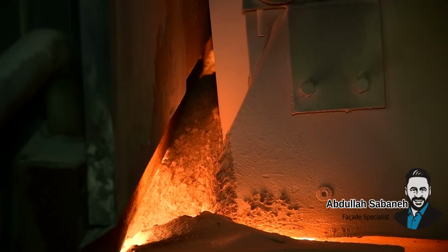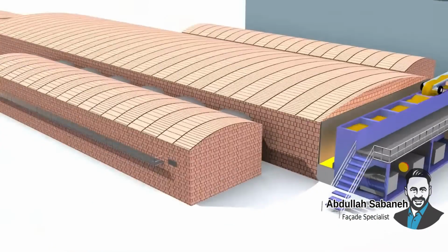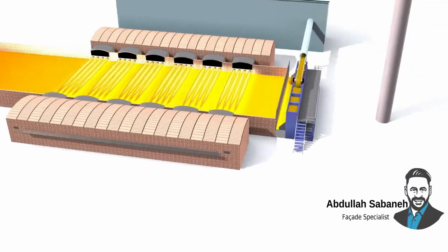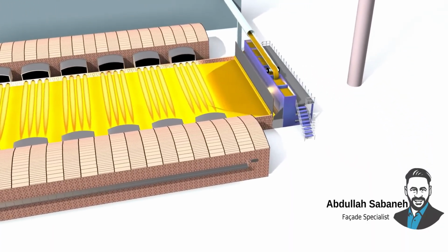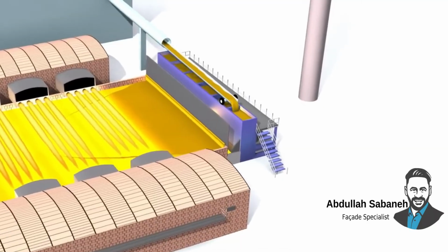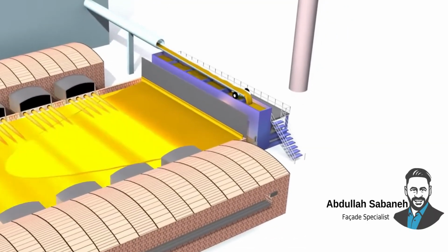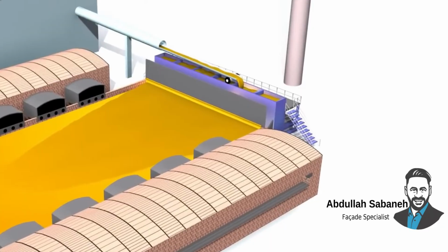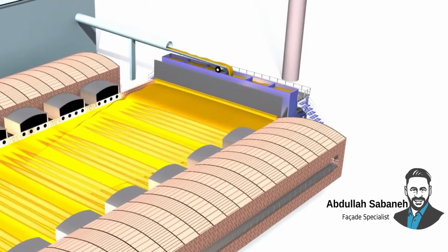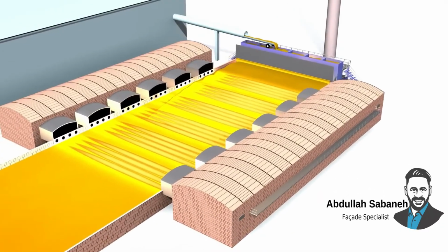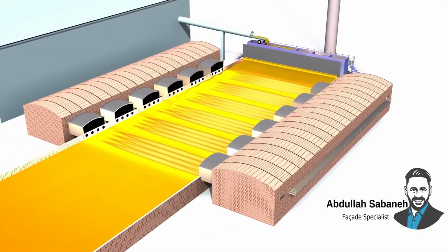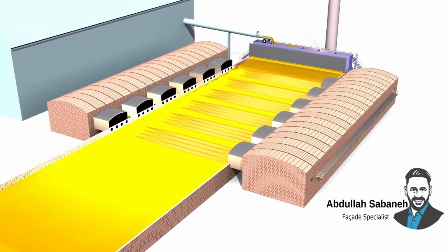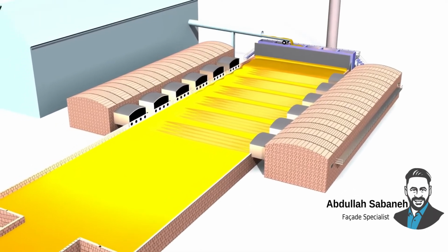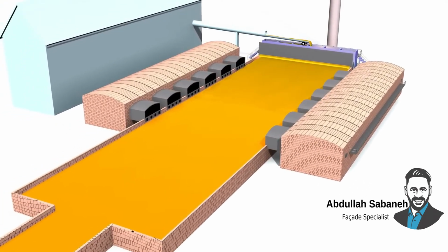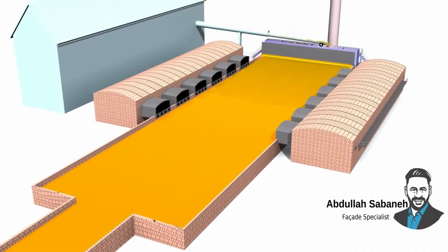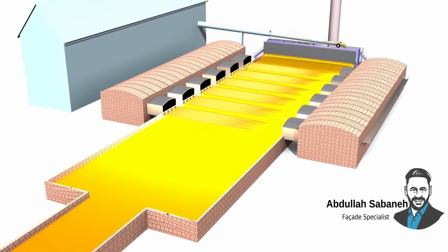And are continuously pushed inside. In the melting zone, the batch of mixed raw materials melts at a temperature of 1550 to 1600 degrees Celsius until it becomes liquid and merges. Melting occurs by heat transfer from the flames located above the glass surface. Chemical reactions between the different elements allow the elaboration of high-quality glass free of bubbles.